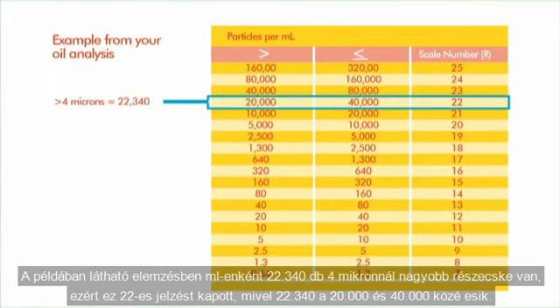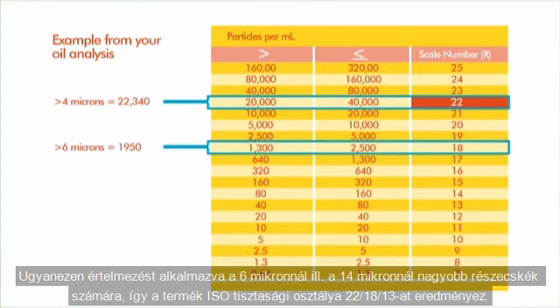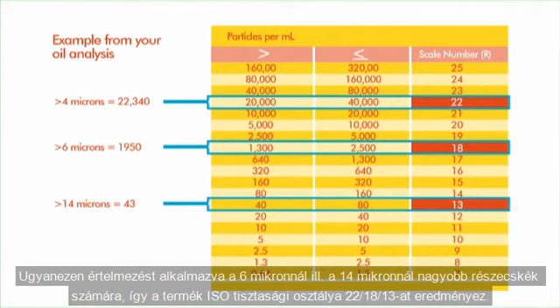As an example, a particle count which reports 22,340 particles per milliliter, which are larger than 4 microns, is expressed as 22, since 22,340 falls between 20,000 and 40,000. The same interpretation system is used for the particles larger than 6 microns and those larger than 14 microns, resulting in a reportable ISO cleanliness code of 22/18/13.